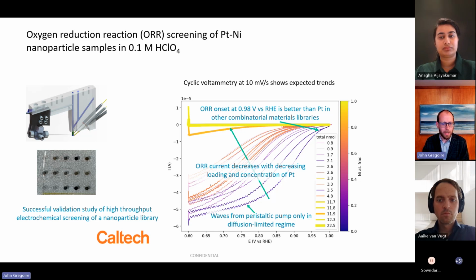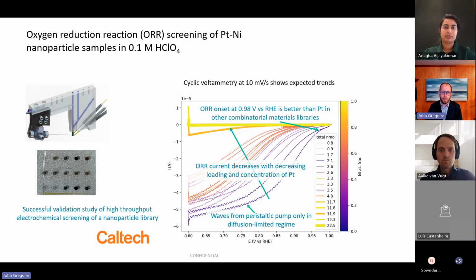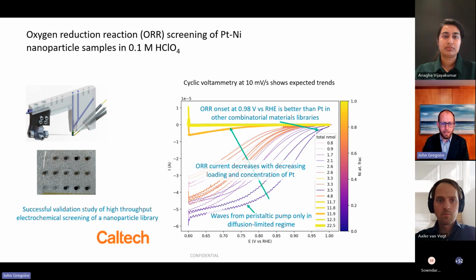All to say, it's very well known that nanoparticle structures are optimal for oxygen reduction, particularly with platinum and platinum alloys. And we're seeing that kind of state-of-the-art performance with respect to onset potential in these films. Also, as you add nickel and dilute the platinum, or lower platinum loading, the cathodic current density marches down as we expect. And an interesting feature is you may notice in the previous slide and in these, there's lots of